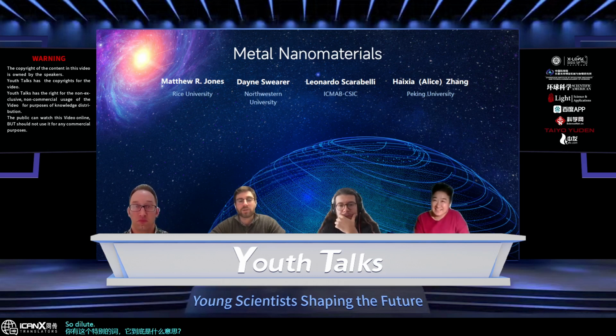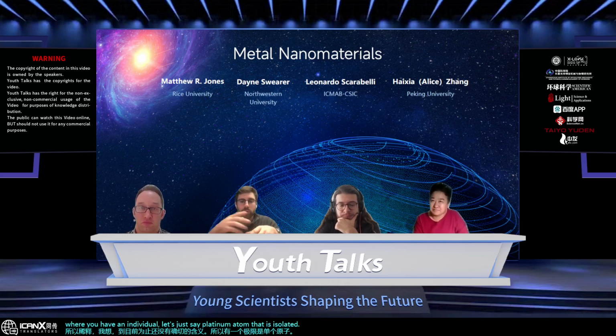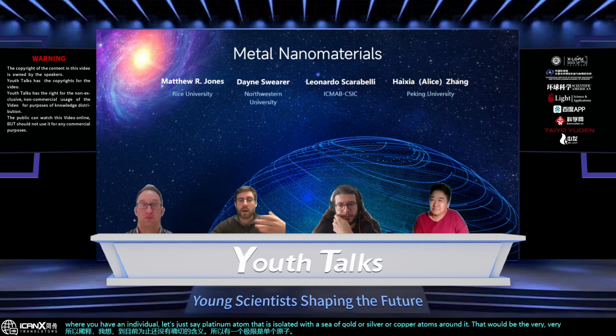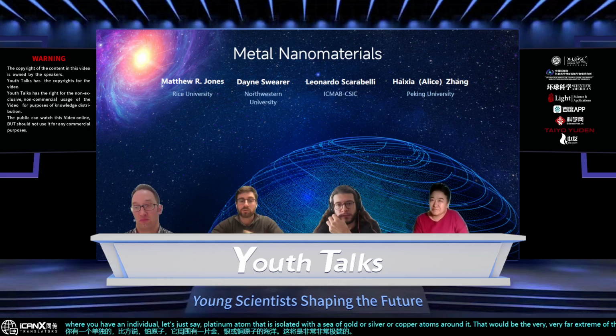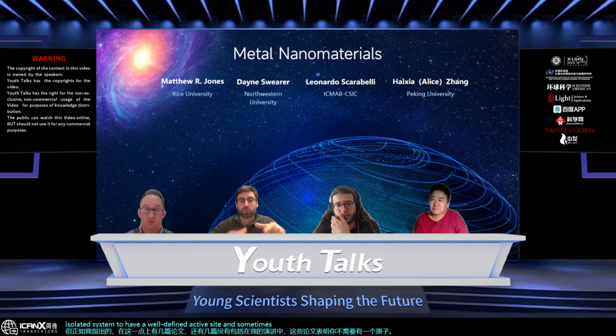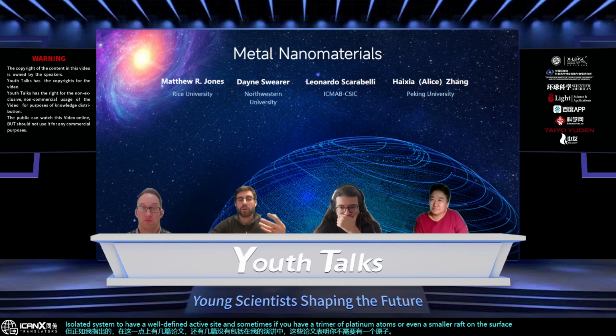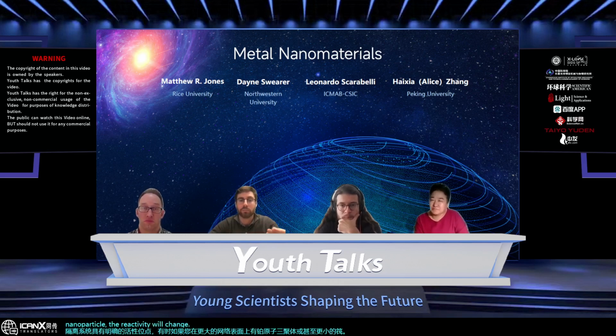So dilute, I guess, doesn't have an exact meaning as of yet. The limit would be the single atom limit, where you have an individual, let's just say platinum atom, that is isolated with a sea of gold or silver or copper atoms around it. That would be the very, very far extreme of this. But as I pointed out, there's a couple of papers at this point, and several more that weren't included in my talk, that have shown that you don't need to have a single atom isolated system to have a well-defined active site. And sometimes if you have a trimer of platinum atoms or even a smaller raft on the surface of your much larger nanoparticle, the reactivity will change and actually could be improved in that way.